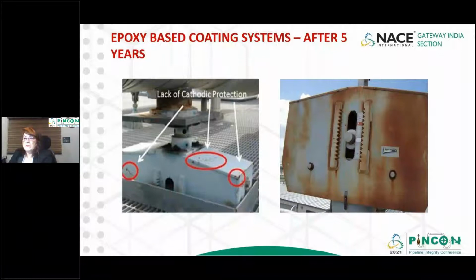With an epoxy based coating system, atmospheric corrosion occurs after 5 years of application. This is where a normal epoxy coating was used. This is the condition of the structure in a coastal area. This photo has been taken from one of the coastal area refineries.